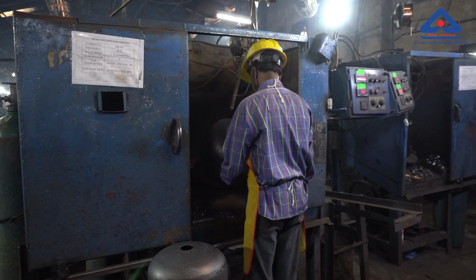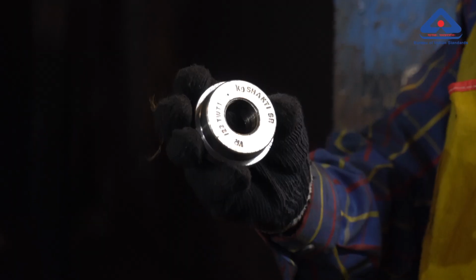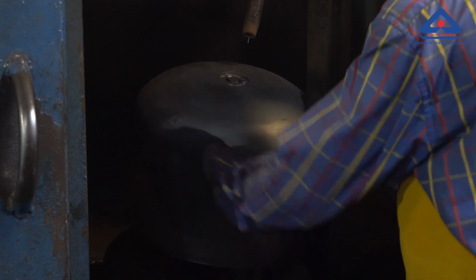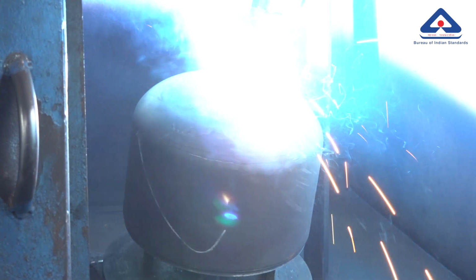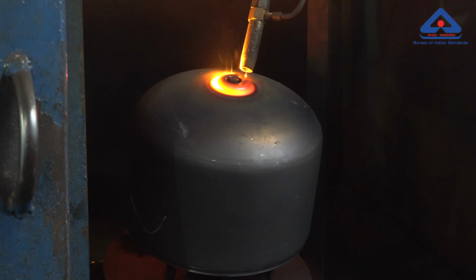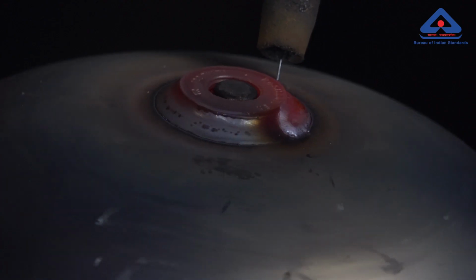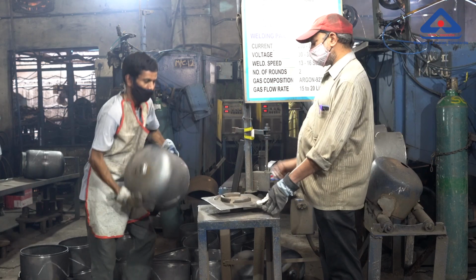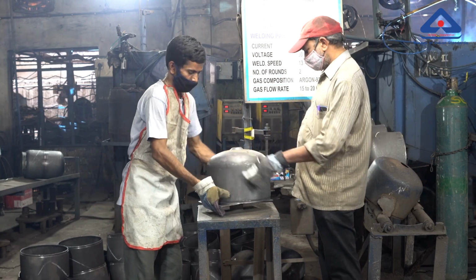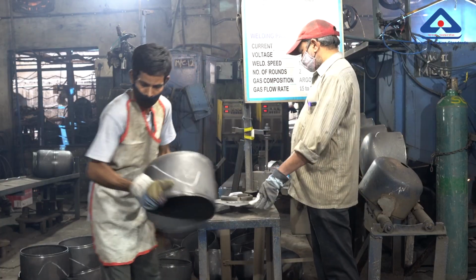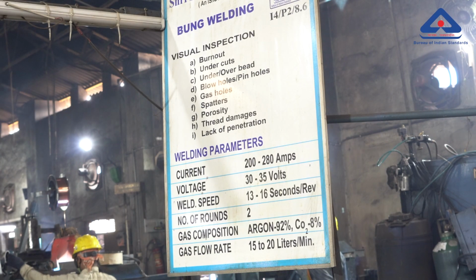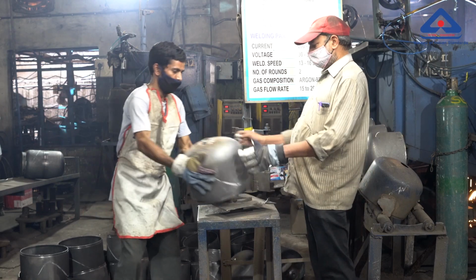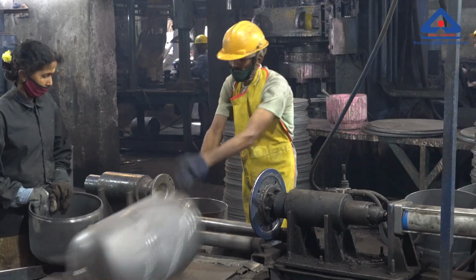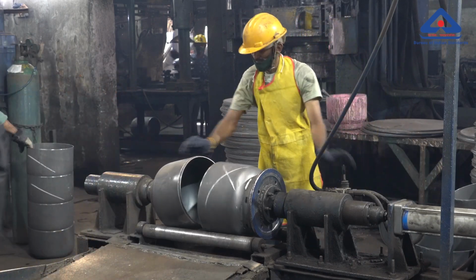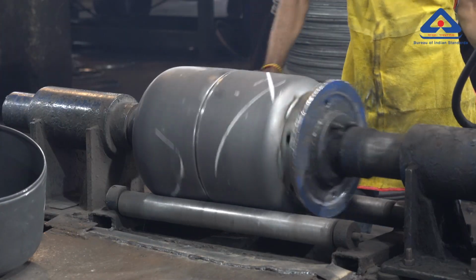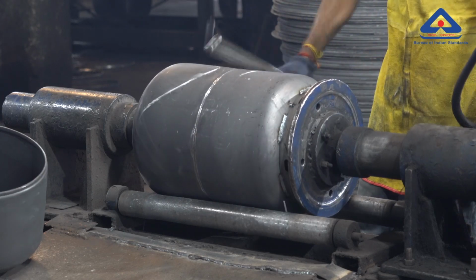Meanwhile, the other half, which has been punched with the hole, is taken for bung welding. The procedure is done with 2 layers welding from outside with MIG argon gas. The bung welding is closely checked in case of any burnout, undercuts, under or over bead, blowholes, pinholes, spatters, thread damages or lack of penetration. Now both the halves, the top with the bung and the bottom with the foot ring, are assembled carefully with the help of pneumatic fixture.